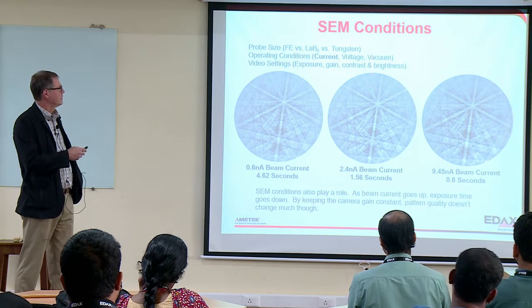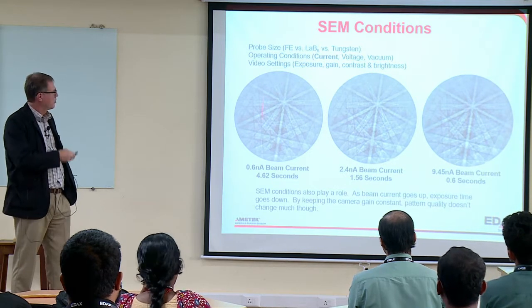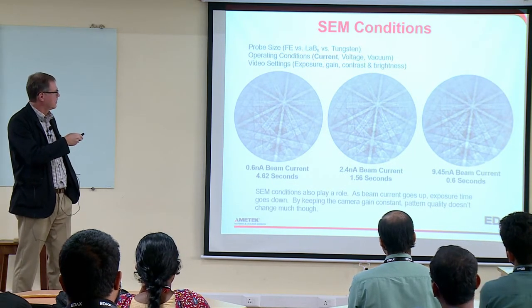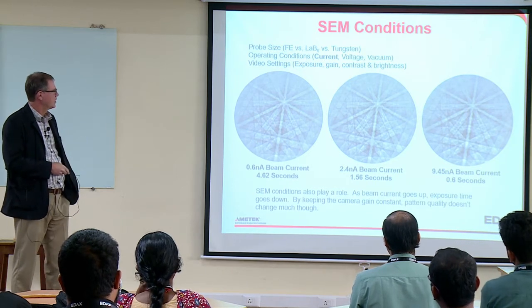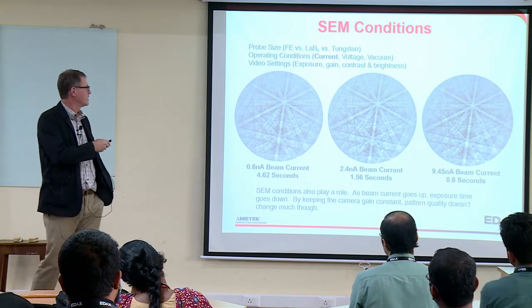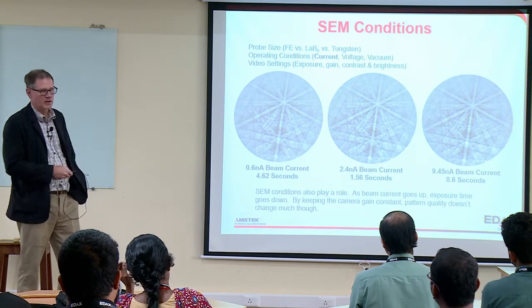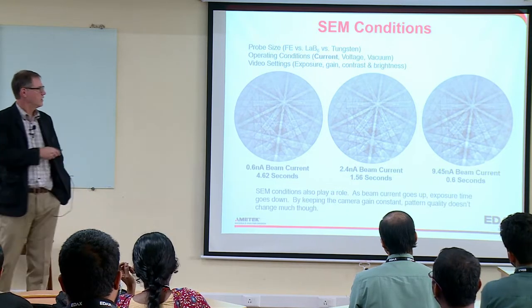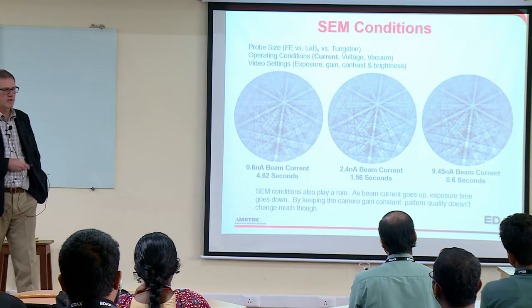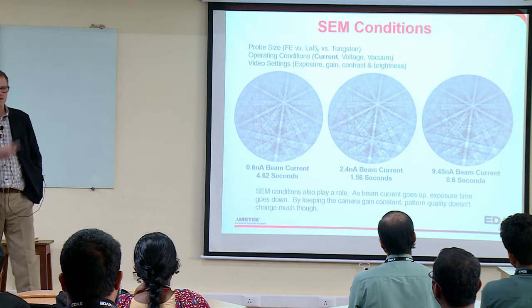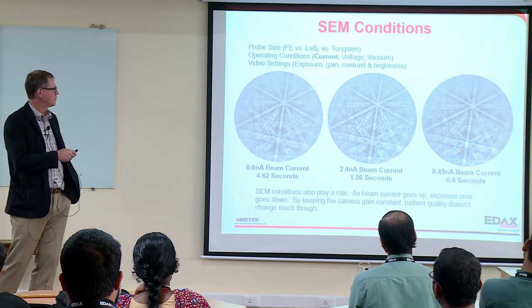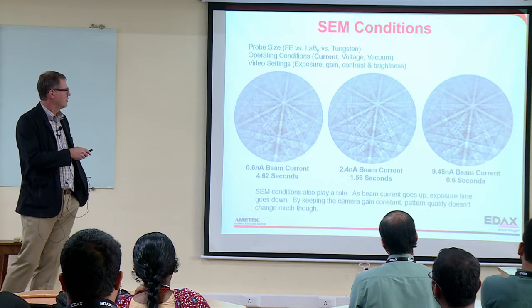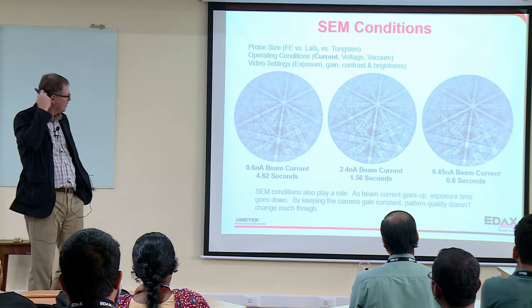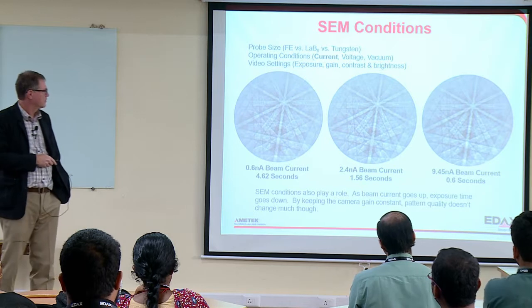The other thing that affects our patterns is the SEM conditions. So the probe size: with a field emission gun, we're going to do better than with a LaB6. I don't see LaB6s much anymore. We can do better than with tungsten. So luckily EBSD and field emission microscopes kind of grew up at the same time, so we get good resolution with those. I've already mentioned the current and the voltage effects, and vacuum as well will affect our results.